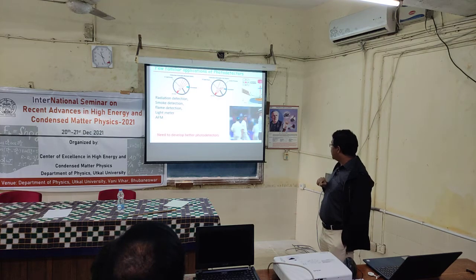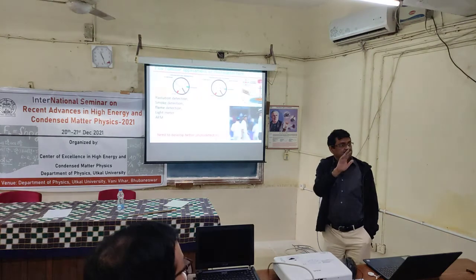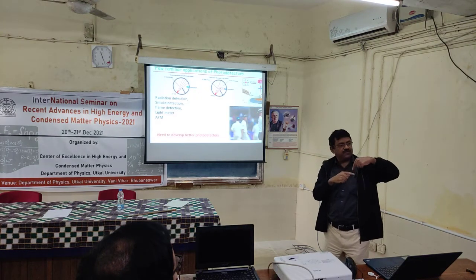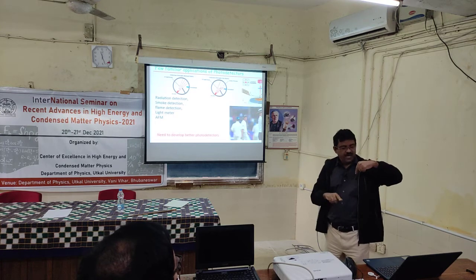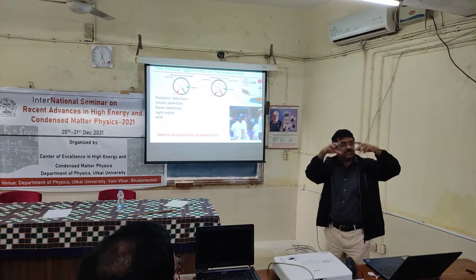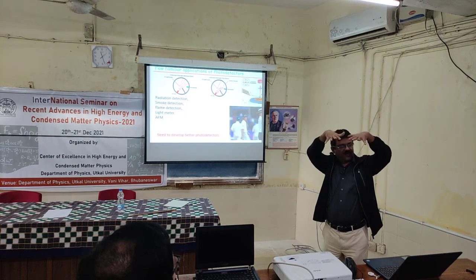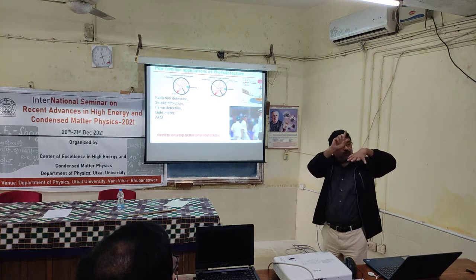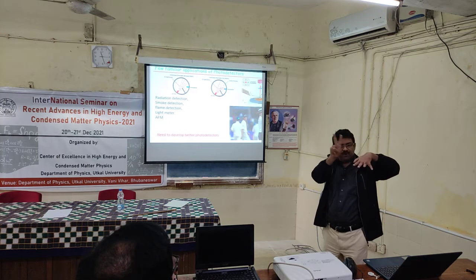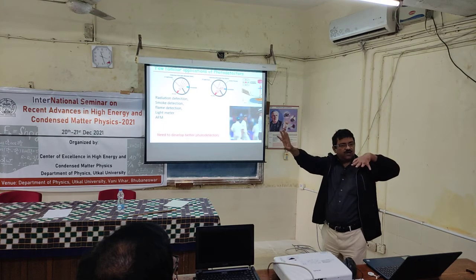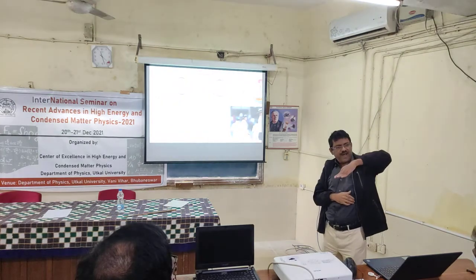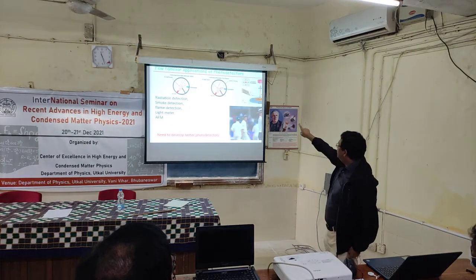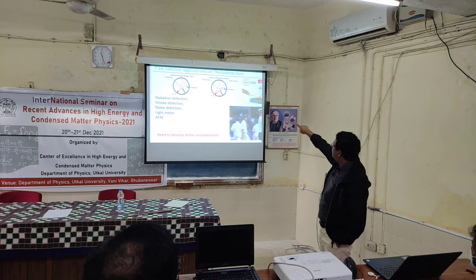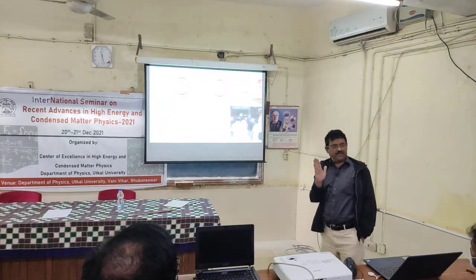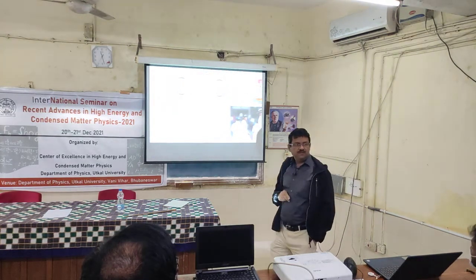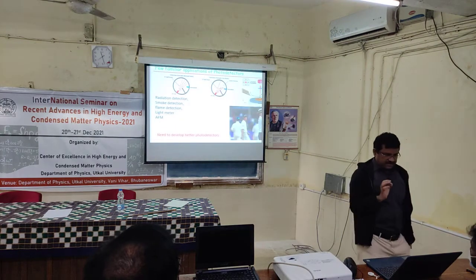Similarly, if you are dealing with atomic force microscopy, a laser light falls on the tip, the cantilever, and gets scattered. If the surface is smooth, it is adjusted in such a way that there are 4 diodes or 4 photoconductors, and they cancel each other so that the photo current eventually will be 0. 2 will be plus and 2 will be minus. The photo current should be 0, but if it is bent slightly, then that light spot gets off center. Either it will be more on A1 or A2 or B1 or B2 depending on how it is getting reflected, and you get a photo current. So there also you need photo detectors.